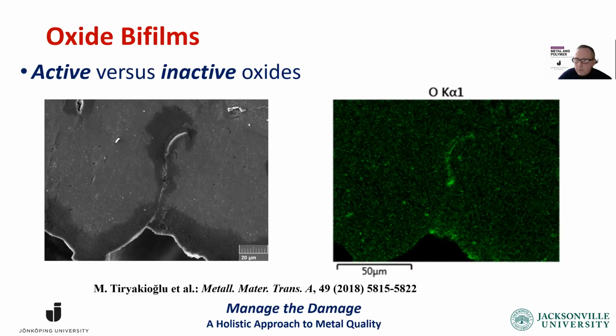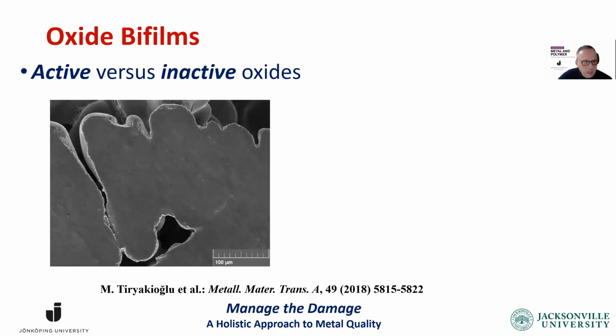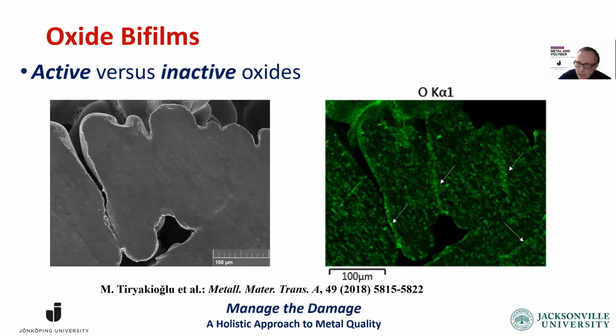And we started looking somewhere else. Okay, we looked at this. All right, there doesn't seem to be anything curious about this feature. Turn the X-ray mapping, and there you see the hiding bifilms shown with the arrows. More bifilms are hiding because the air in there that we expanded, we thought, to the maximum, was not sufficient to open up all the bifilms. So the huge pore that we looked at was only a part of the damage. There's more damage in there that just did not open up.